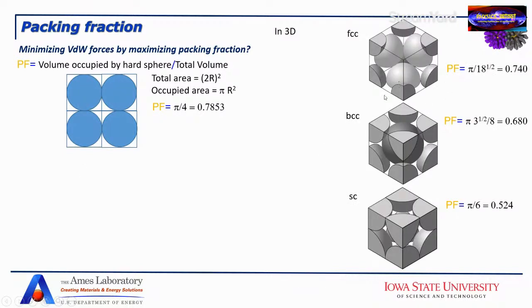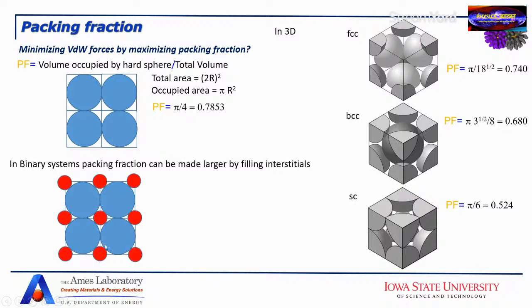In 3D, you can do the same thing. For the packing fraction, there are the FCC, BCC, and simple cubic, and you see that FCC is the most efficient way to pack equal spheres. In binary systems, you can improve. In binary systems, you can reach packing fractions that are even larger than these, because in this two-dimensional case, you can pack with additional circles in the interstitials, and these circles occupy some additional space. Now what you see is that the packing fraction here is just a number, while here it is a function of the ratio between the radius of this particle and the radius of the other one. So we define a parameter gamma, which is the ratio of the smallest to the largest nanoparticle. In general, the packing fraction will be pi over 4 plus some function of gamma.